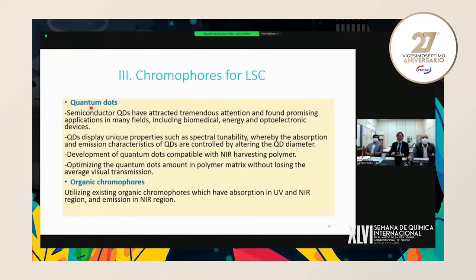Actually, quantum dots attracted tremendous attention and found promising application in many fields, including biomedical, energy, and optoelectronic devices. Also, the important characteristic of quantum dots is spectral tunability, whereby the absorption and emission characteristics of quantum dots are controlled by altering the quantum dot diameter. So if you want to have a very good LSC with high efficiency, the emissions of these quantum dots should match with the NIR harvesting polymer. So optimizing the quantum dots amount in polymer matrix is also important.